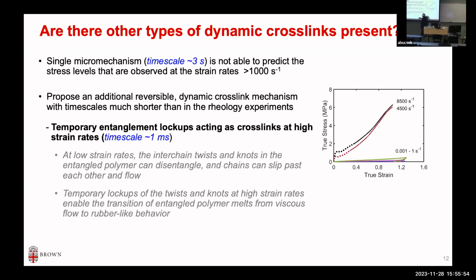So very intuitive. At slow strain rates, you can have this disentanglement, your fluid-like flow, driven by the interaction between the polymer chains, more like friction. But at very high rate, there's a lockup. That lockup leads to this behavior. That's our assumption. We have proposed basically 2 mechanisms from the experiment. All this is based on first order kinetics from the experiments. We have 2 mechanisms, and one has a time scale of milliseconds that we found later.